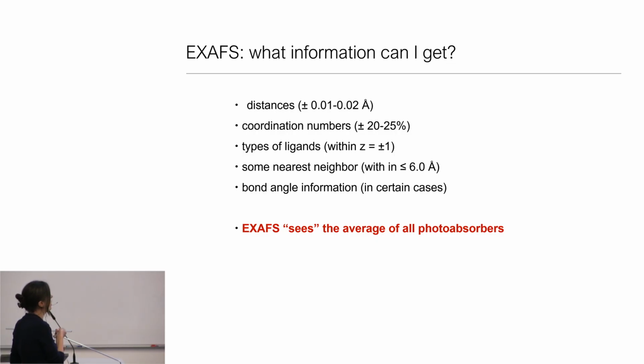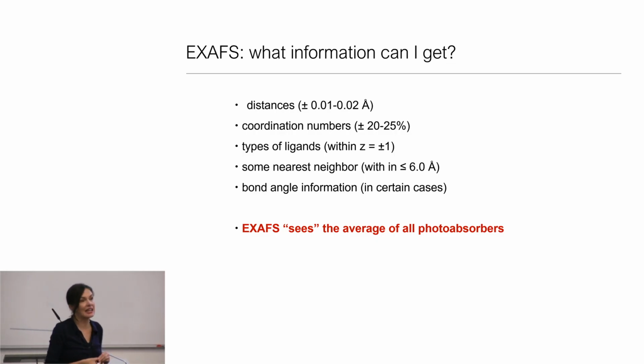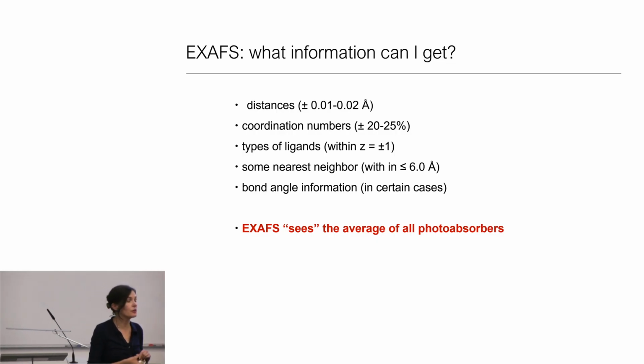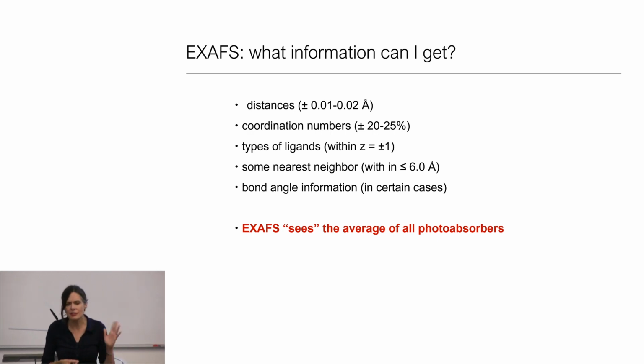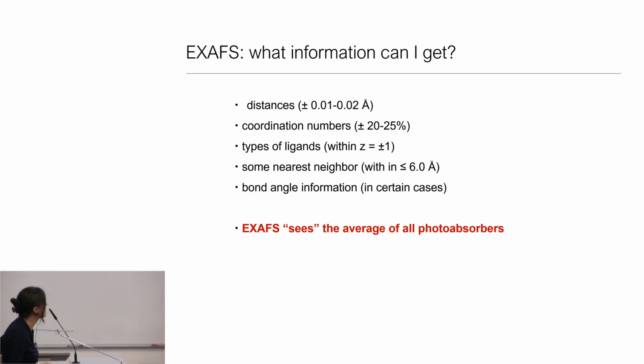This will depend on the quality of your EXAFS, but I would say a maximum distance is 6 angstroms or so from the photoabsorber. And in certain cases, like well-ordered cases, you can get bond angle information. But standard EXAFS sees the average of all photoabsorbers. So if you have a mixture, you see the average of a mixture. And that can be one of the challenges that you can sometimes get around with certain high-resolution X-ray spectroscopy methods, but certainly not in standard EXAFS.